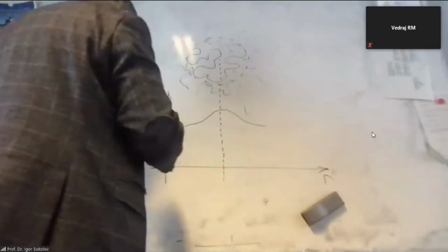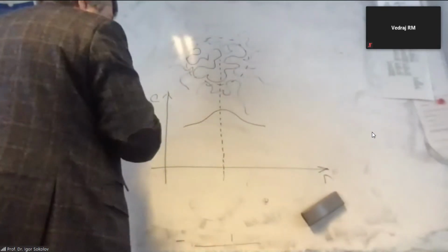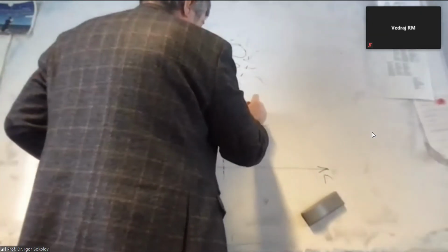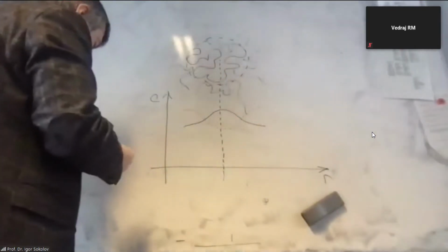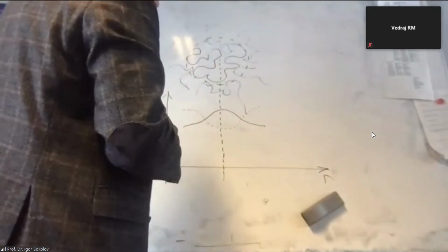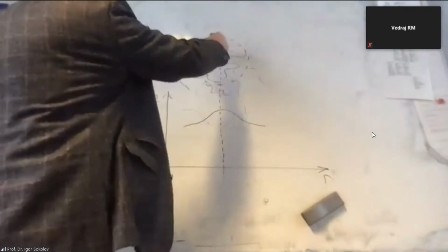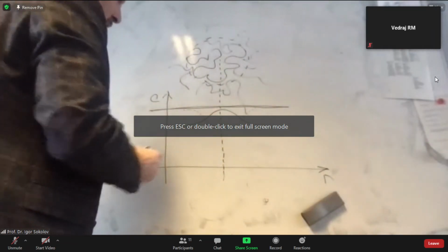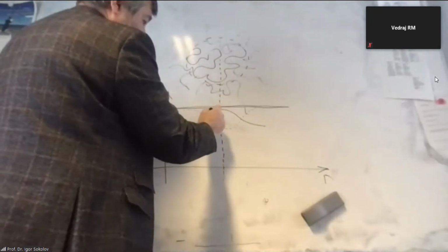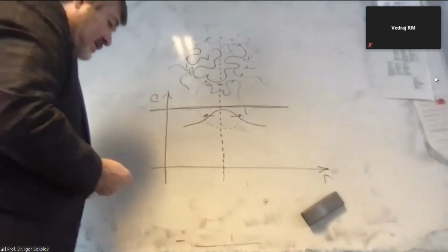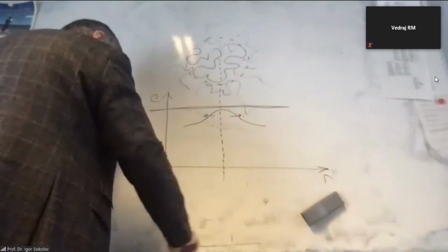This is this Gauss, and the concentration of monomers of the other polymers is like this, because they are expelled due to the excluded volume interactions from the place which is occupied by this, but the total concentration, the concentration in the whole fluid, is constant. So these guys are, of course, exerting the osmotic pressure on this bag, trying to make it larger, which leads to swelling.